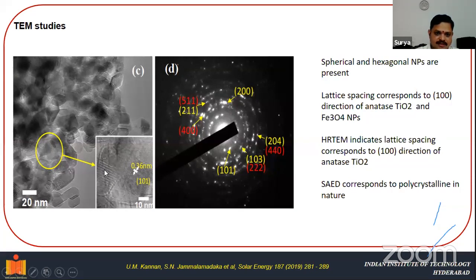planes. From this, we try to calculate the gap between the lattice planes. It is a very powerful technique to determine the structure of the material, to determine the particle size of the nanoparticle. So from the image, we have calculated the particle size. We also tried to calculate the gap between the planes. The gap between the planes is found to be around 0.36 nanometers.